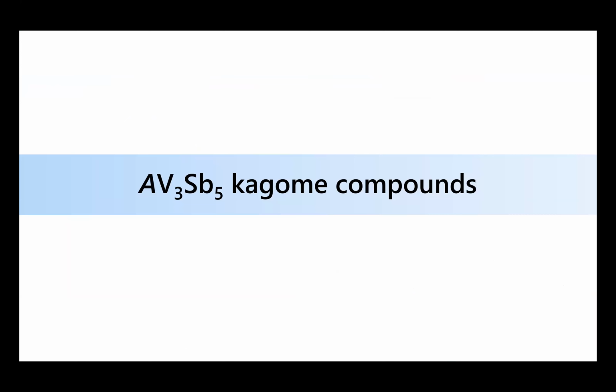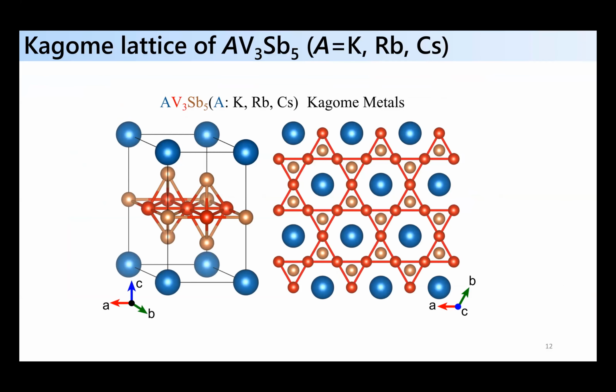Okay, so the first material I want to talk to you about are these so-called 1-3-5 compounds. What the crystal structure looks like is the following. This is a perfect kagome net of vanadium ions, and each vanadium site is coordinated by antimony. These V3Sb5 blocks are then separated by planes of alkali metal ions, okay? And so it's a quasi-two-dimensional crystal structure, and it exfoliates rather readily, and it's also quasi-two-dimensional electronically. There are 3 variants that are stable in the vanadium family, which are potassium, rubidium, and cesium.